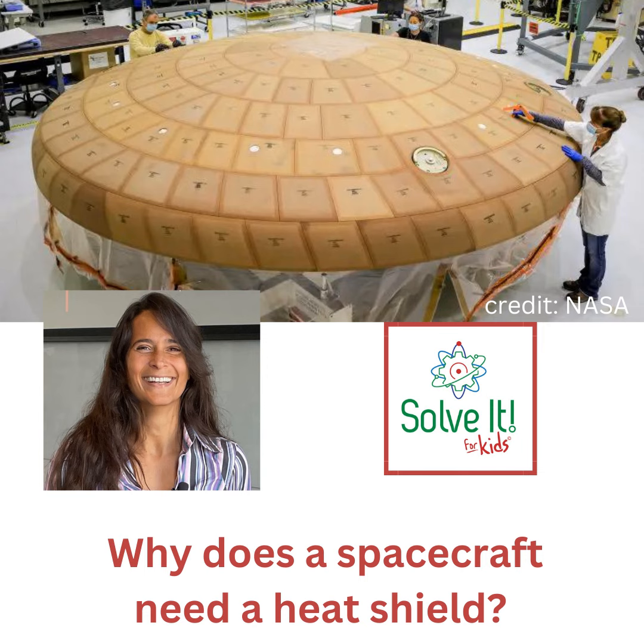So in terms of its similarities, the material we use for the thermal protection or the heat shield on Orion is called Avcoat. And that was used on Apollo as well. But over time, we've been able to, I want to say this in the simplest way possible, make improvements to the mixture so that we can manage what they call the thermal response, what the material does when exposed to heat. And so, you want it to have a certain density. You want to understand the amount of weight you're going to have to carry. So you're sort of trading all of these variables of we'd like a material that is lightweight, but also does the job of absorbing that heat, ablating off and getting rid of that heat energy. But both Apollo and Orion use the same material. The primary difference between the two is we're configuring it or installing it differently than Apollo did.